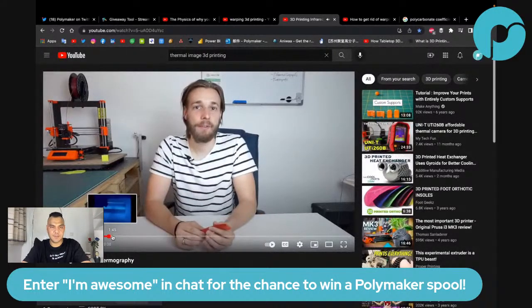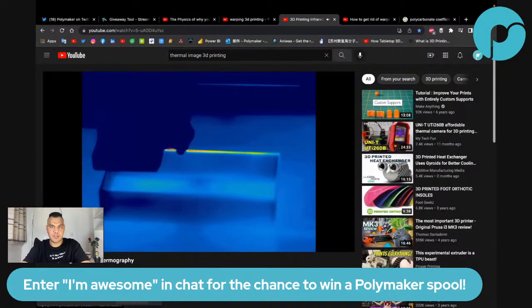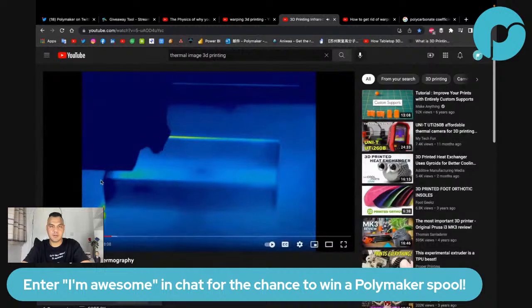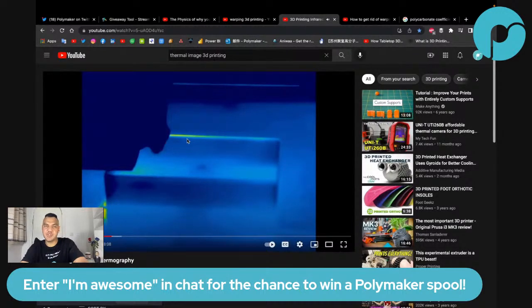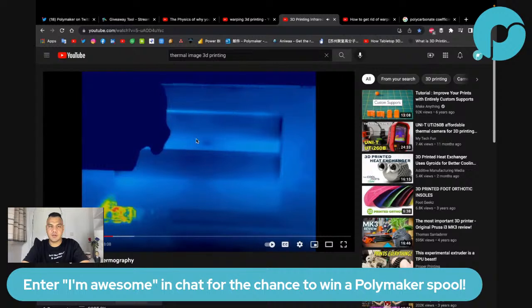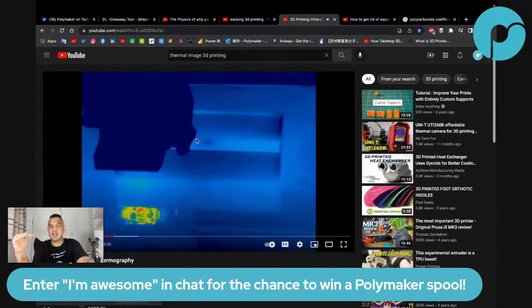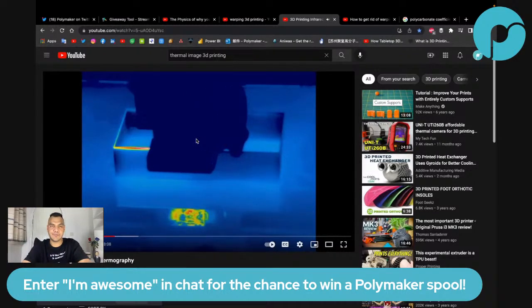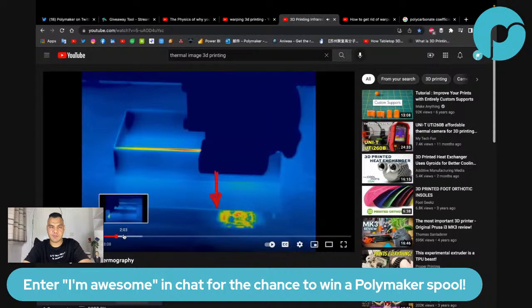And later on, this video simply visualizes the temperature gradient. Okay, so you can see the temperature here, right? So this is without cooling fan. We're printing at 40 millimeters per second, and he was saying it stays hot around 6 to 7 millimeters. But stay hot means going from 200 down to 80, 70, 60 directly. You can see the reflection of the nozzle in the heat bed itself.